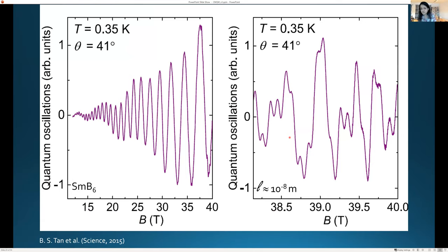Typically, if we saw oscillations, we would associate it with electron-like quasi-particles. But if we were to do that, there's this massive dichotomy with this apparent mean free path, which means something has broken down. And indeed, it could be the assumption that these are electron-like quasi-particles which is not correct. I totally agree.